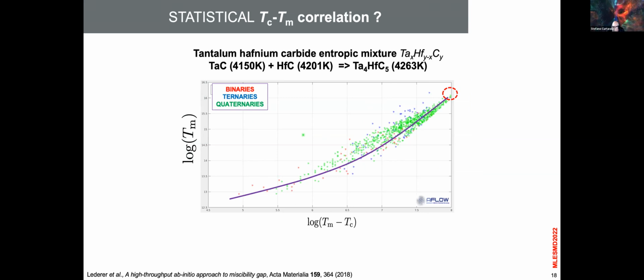So to get very high melting point systems, you need to have a very low miscibility gap and many species. In fact, look here, the highest known melting point system, which is tantalum hafnium carbide, Ta4 hafnium C5, has a higher melting point than the two constituents. TaC is this temperature, hafnium carbide is this temperature, this is higher. You see, you get 60, 70 Kelvin more.